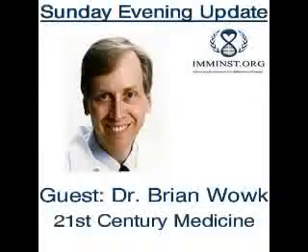Now, as far as the treatment question goes and prognosis for cryonics patients, I don't lose too much sleep over it because I don't think it actually causes loss of information. When these fractures form, they're forming at cryogenic temperatures when the material is already solid. In fact, solidification of the material is sort of a precondition for fractures to form, which means that when a fracture face forms, the faces would be expected to be clean and matching, which means whatever future repair devices you imagine going in there to infer the original structure and information would probably have complete information to work with. So I'm not too concerned with it from a point of view of information loss.